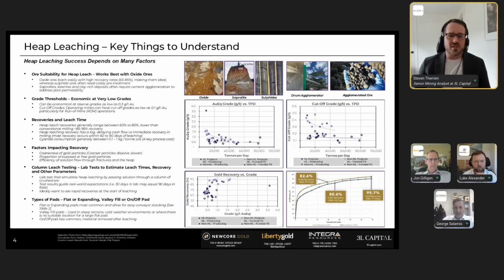So heap leaching success depends on a bunch of factors such as ore oxidation, permeability, grade, recovery, leach times. Oxide ores are ideal for heap leaching, offering high recovery rates. Sulfide ores can require costly pretreatment. Saprolites and laterites, weathered tropical ores, are great candidates as well, but typically require cement agglomeration due to the clay content. Clay-rich deposits can be challenging due to poor permeability, but you can get over that with agglomeration.